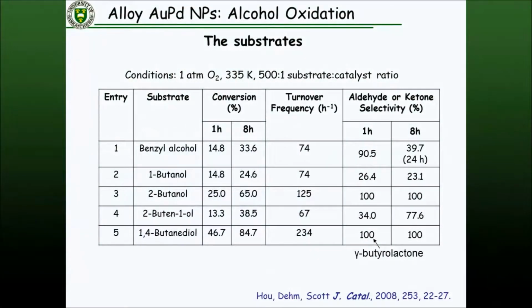And it turns out we can get wonderful catalytic activities for alcohol oxidation. This is at just over 60 degrees Celsius in water, 1 atmosphere oxygen, with everything from benzyl alcohol, primary alcohols, secondary alcohols, allylic alcohols, to diols. All of them are reacting. Diols are very interesting to get pure selectivity to the lactone. In a lot of these systems we started to see fairly good selectivities to the aldehyde in short periods of time, and then over longer periods you get more and more acid buildup. So the idea is that you form the aldehyde and then the aldehyde further oxidizes to the acid.